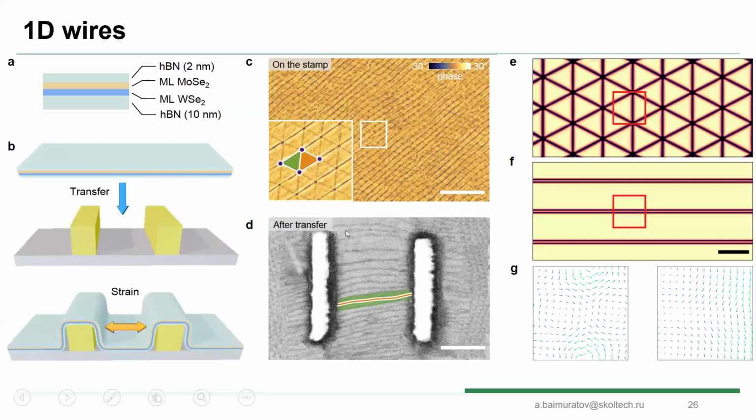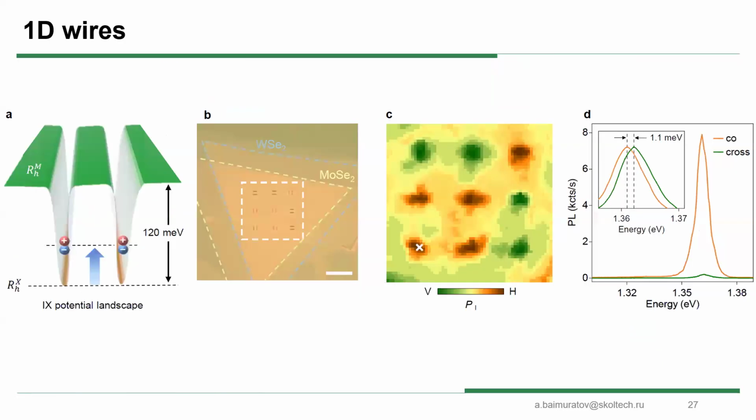And we prove it not only with electron microscopy, but also this is why we decided to use this system. In previous work we calculated energies, and we know from experiment the energies for these two stackings, for green stacking and for orange stacking. And we know that in the excitonic picture the difference between these two excitons will be around 120 meV.